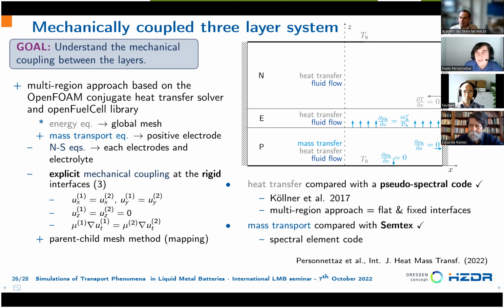And we also simulate solutal and thermal together, and we saw that usually what you have is a strong heat generation here in the electrolyte and a stable profile here, and the flow due to solutal convection mixes this stable profile very well, making the temperature distribution in the layer almost uniform. Yes, it will make the lower part even more stable. The thermal effect.